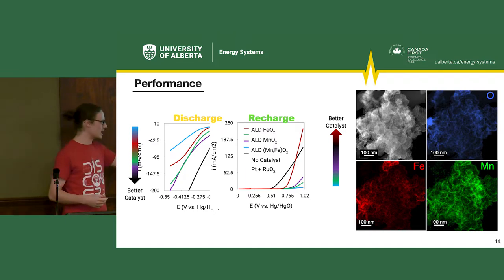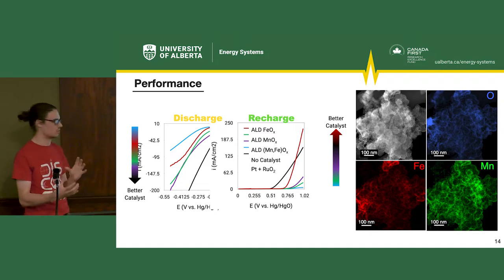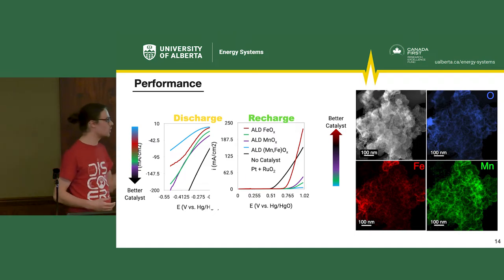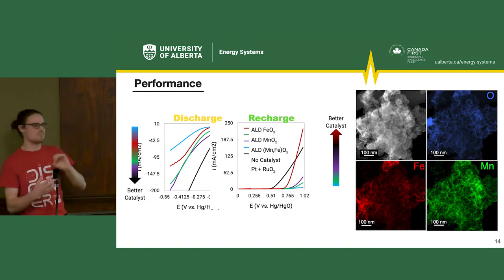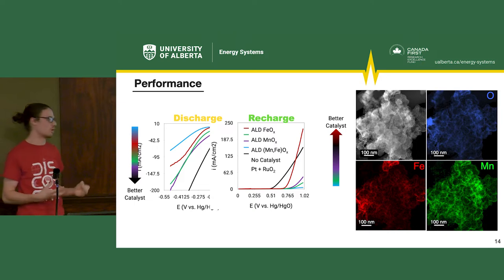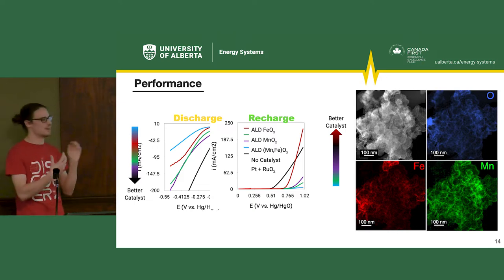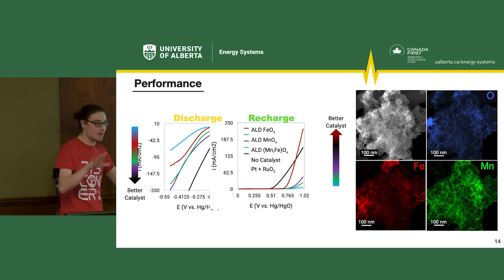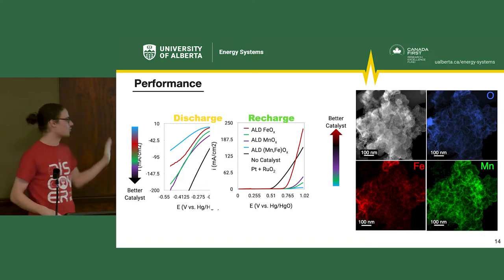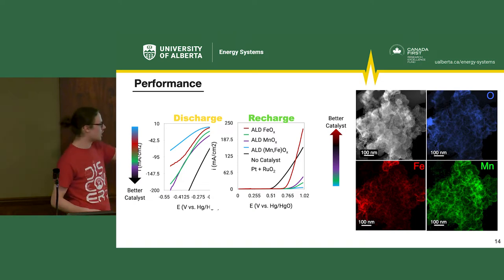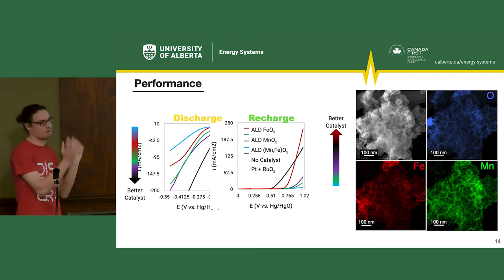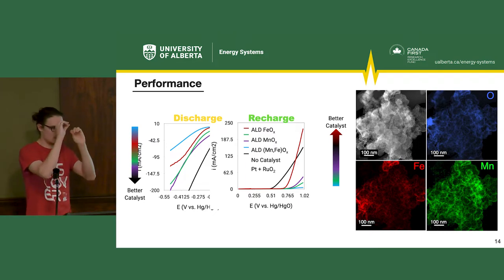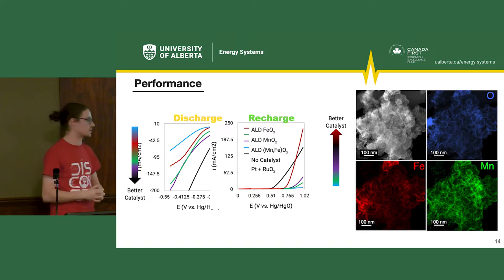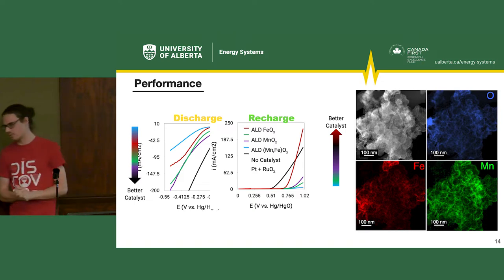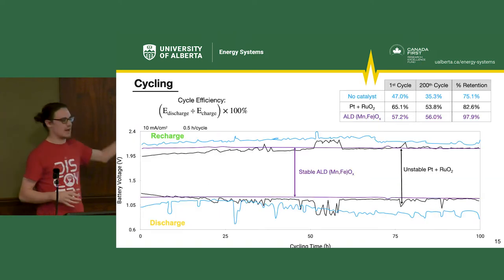However, look in the recharge reaction, somehow we've lost the potential. So the iron there in red is doing great. The purple down there, not quite as good. So somehow the manganese got in the way of the iron's working for the recharge. So it's still a work in progress to get the best of both worlds. And then we're mapping it with x-rays again, you see oxygen, iron, manganese, and they're all overlapping, right? They're not layered. It's all one mixed oxide. That's great news.